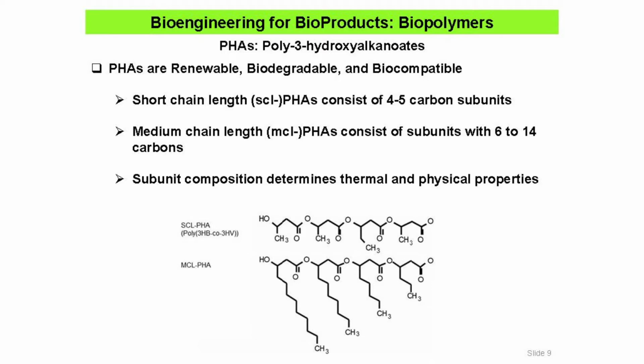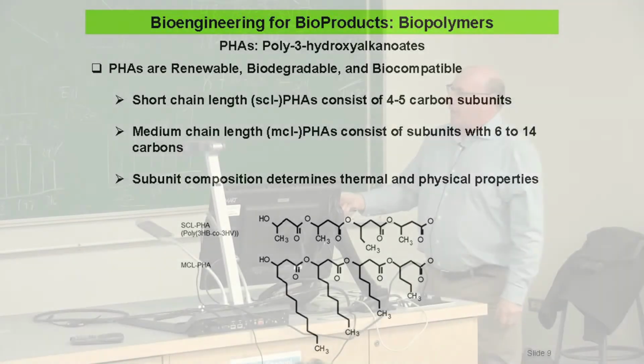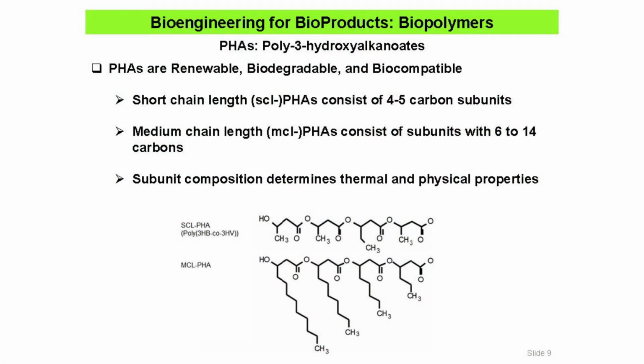And the composition of these polymers determines their thermal and physical characteristics. And you can see that if you had a polymer that is 100% 4-carbon subunit consistently, it would stack on itself very, very easily, right? It would become very crystalline. So you can get very high tensile strengths, but not very elastic. Whereas the medium chain length ones have variable chain lengths that interfere with stacking, with crystallization. So depending on the length and the proportion of the longer side chains, they're not even crystallizing, not even a solid at room temperature. They're a liquid that's sort of sticky or tacky, right? So we can vary the physical and thermal properties depending on the side chain composition.